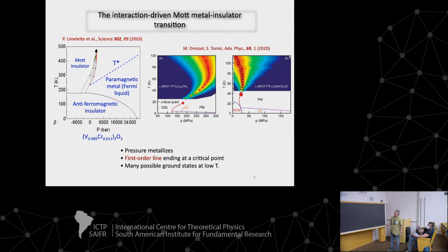a paradigmatic Mott insulator, where you have this line here where there is a first order phase transition between a metal and an insulator. I'll show you conductivity data later. You have actually a region here, because this is a hysteresis region where you have coexistence between the two phases. But there's actually a single thermodynamic line here separating these two phases. And you see that it ends at a critical point at a finite temperature here.